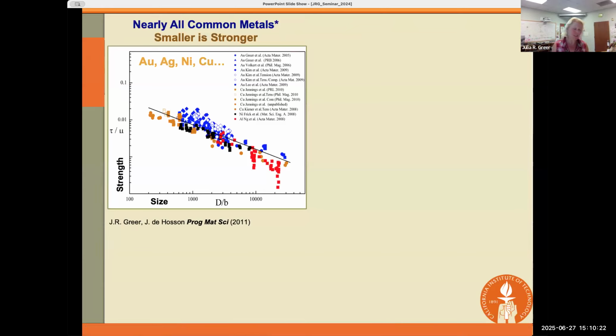Now, hopefully I've convinced you at this point that they're very lightweight, but I have yet to show you why we might expect these materials to be stronger. What I'm showing you here is yet another log-log plot, and this plot represents the strength of many different common metals, like gold, silver and nickel, etc. What this plot shows us is that in their single crystalline form, all metals become stronger when you reduce their dimensions down to about 100 nanometers. So that tells us that gold or copper, something we know to be very malleable, becomes as strong as steel when you reduce their dimensions to the submicron level.